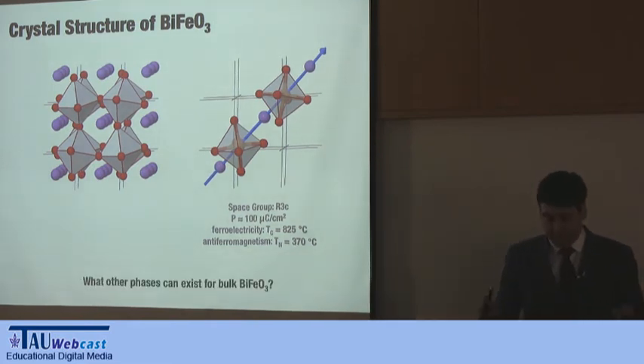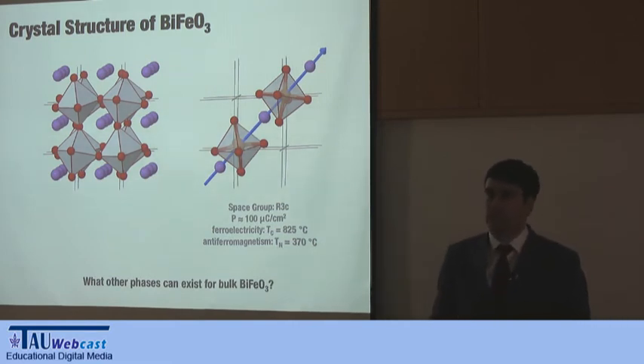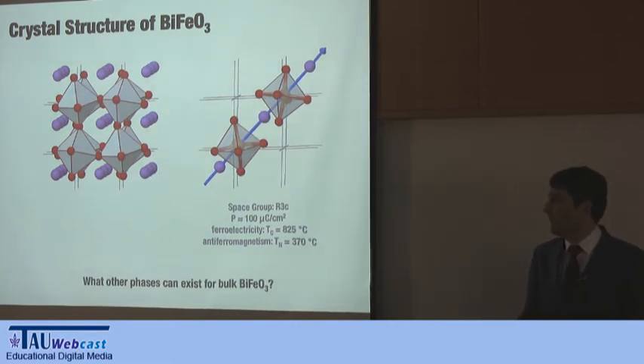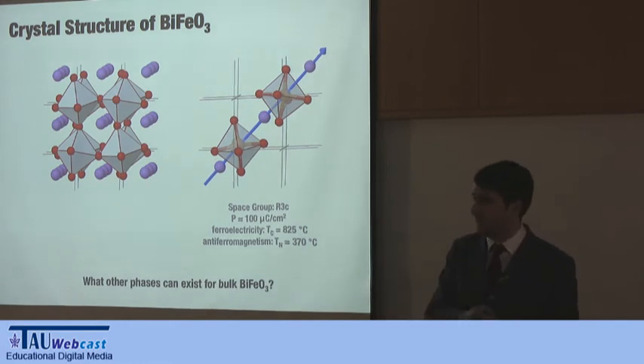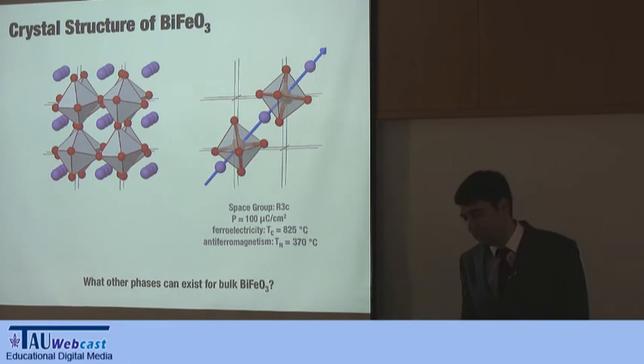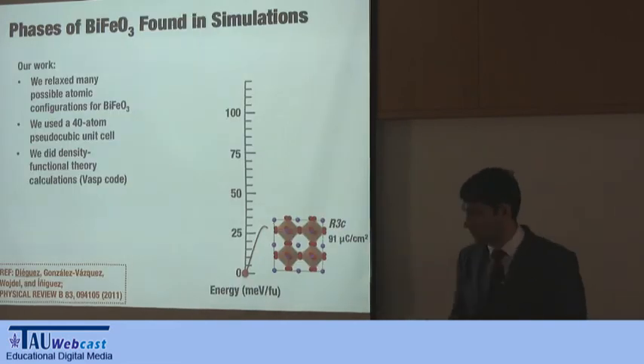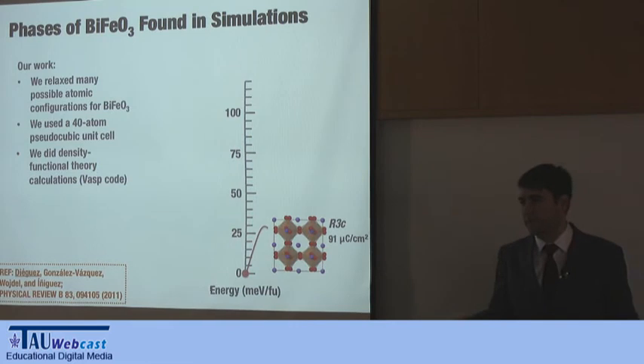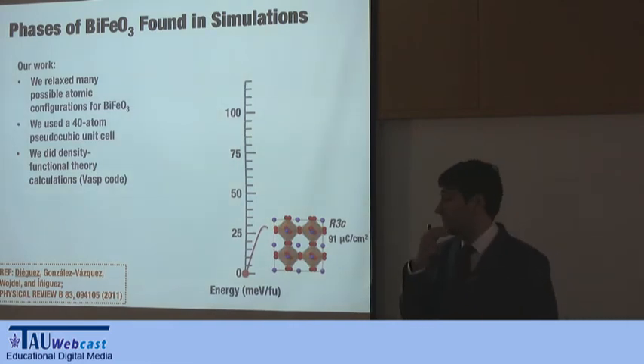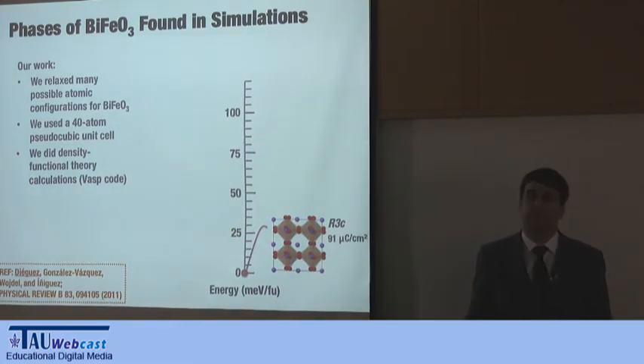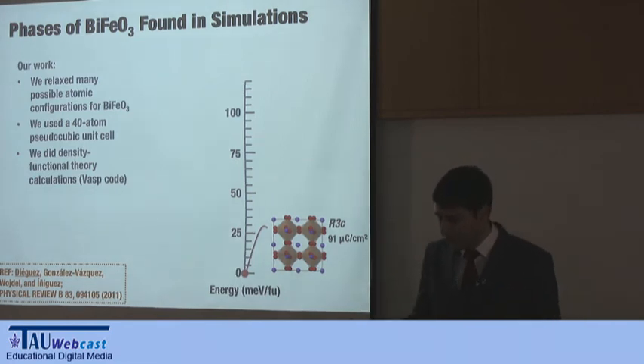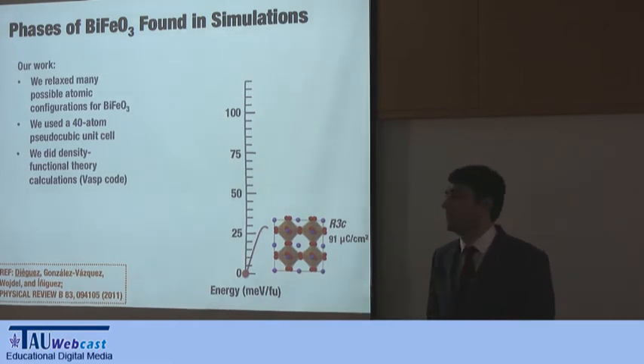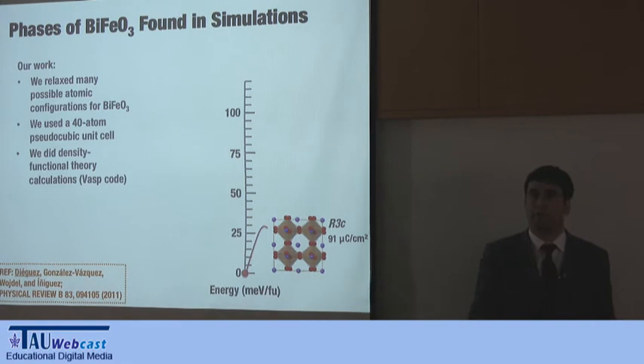Now, a question that we can address: are there other metastable phases of bismuth ferrite that maybe have better properties if we can make them stable? And this is ideally suited for the kind of methods we use. We do this by coming up with trial guesses, that you heat a little bit so they get disordered, the atoms begin to move, and then you let them cool down and see where they want to go.